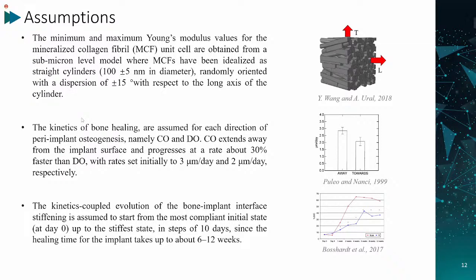The seal (CO) rate is 3 micron per day, and from the old bone to the implant, the progress (DO) rate is 2 micron per day. So seal is faster than the DO progress. So the assumption 3: the kinetics coupled involution of the bone implant interface stiffening is assumed to start from the most compliant initial state, day 0, up to the stiffest state in steps of 10 days, because the healing time for the implant usually takes up to about 6 to 12 weeks.